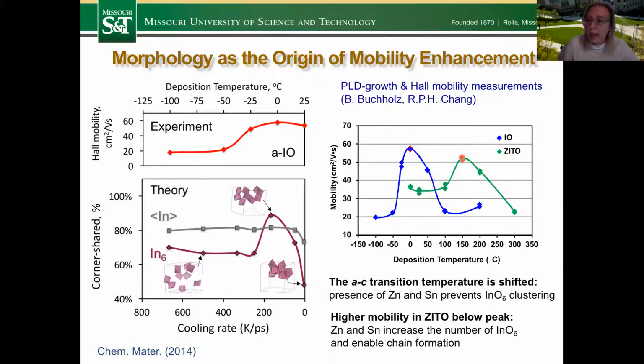So again, the red point in Zito, zinc indium tin oxide, corresponds to the transition to X-ray amorphous. And again, we have a peak just at the onset, but based just on the structural motifs and the morphology in zinc indium tin oxide, we can tell that indeed the transition temperature should be shifted as expected. Of course, we have more components in this system, so there will be a higher temperature range for the crystallization, which is good and practical from an application perspective.